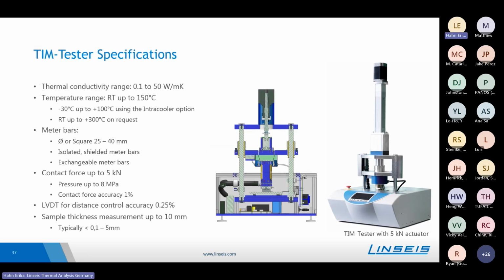Mainly the instrument is used from room temperature up to 150 and can be used for materials with a thermal conductivity range of 0.1 to 50 watt per meter Kelvin, but mainly the thermal interface materials go up to 20 watt per meter Kelvin, so that the upper limit can be used for some further materials. Also, the meter bars, as well as the temperature range, can be customized a little bit so that the temperature range can also be extended to lower temperatures as well as high temperatures up to 300 degrees Celsius.